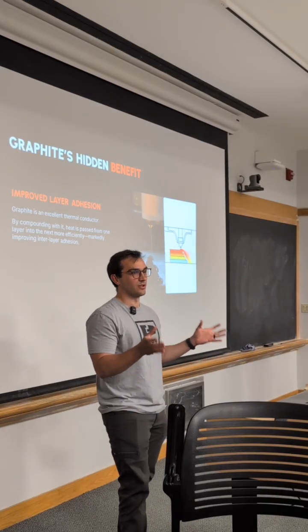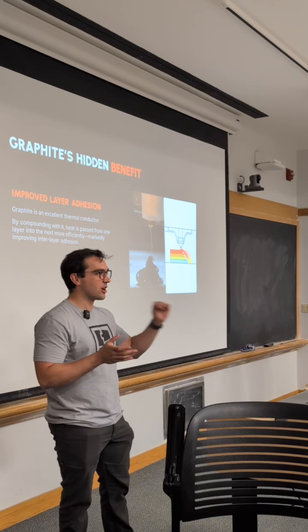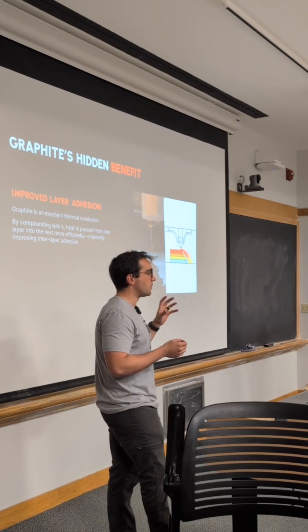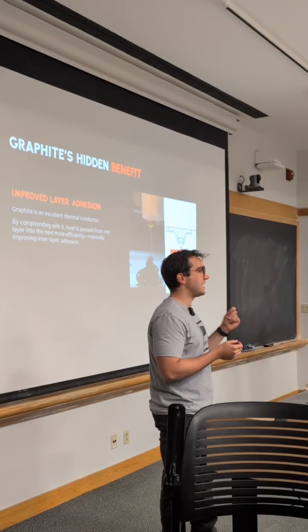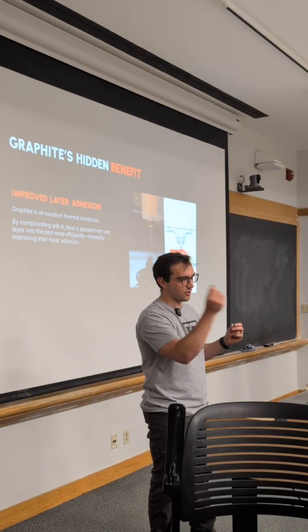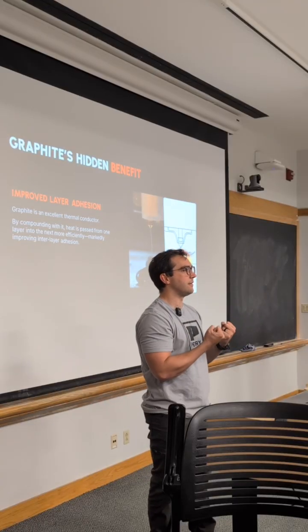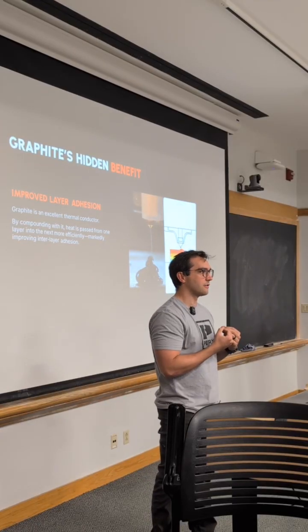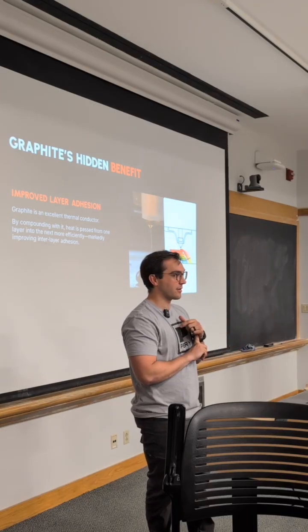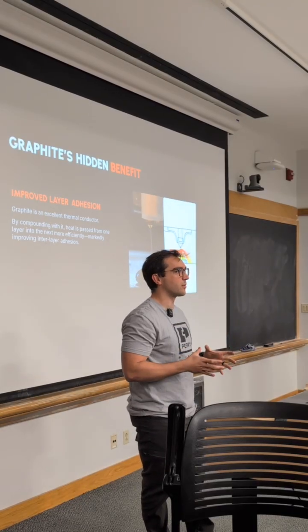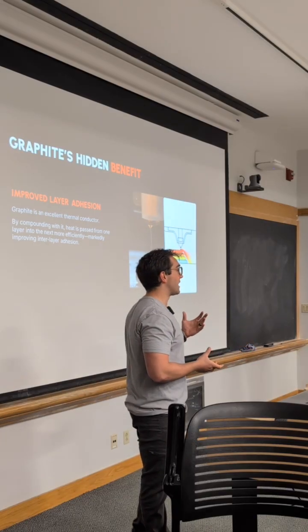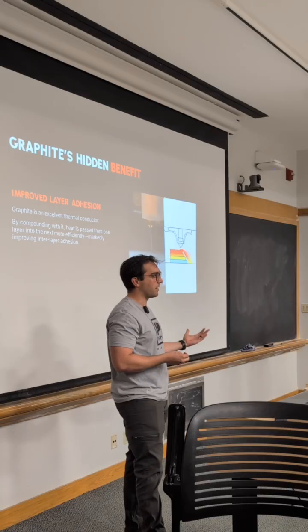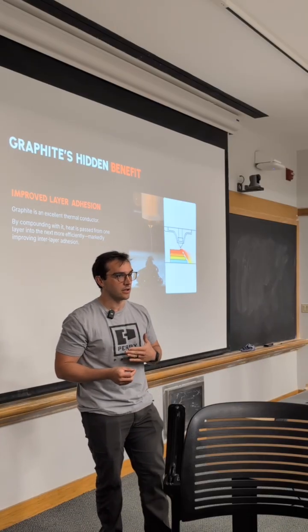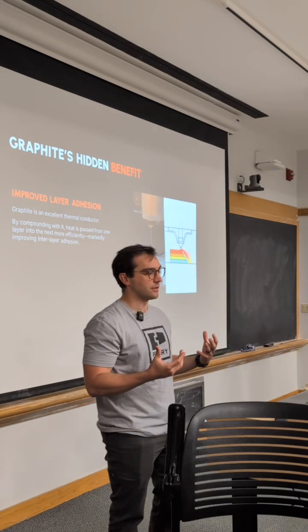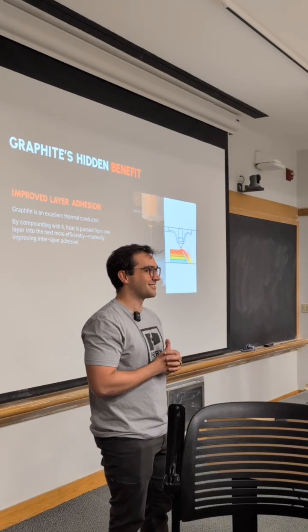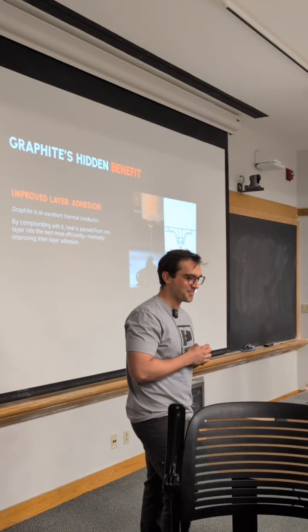Graphite's an excellent thermal conductor. And when we're printing layer by layer, laying down hot layers of polymer, we want the different layers to conduct heat between each other. Because then your currently printing layer, you can dump all the heat from that hot polymer right into the prior layer to, A, help set your existing layer, but also to provide a more uniform thermal gradient throughout the part. So the graphite actually provides us a processing aid as well, where we're able to get better interlayer adhesion. We get all these mechanical properties out of the material, and the part's black, which is cool. It helps check some boxes for us.